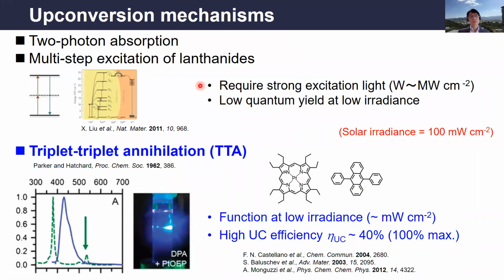There are a few upconversion mechanisms, including two-photon absorption and multi-step excitation of lanthanides. They are very useful for biological imaging, but unfortunately they require strong excitation light, like over watt per square centimeter. If you think about solar irradiance, it is 100 milliwatt per square centimeter for the whole wavelength range. So it cannot give you a high upconversion quantum yield at such low excitation intensity.